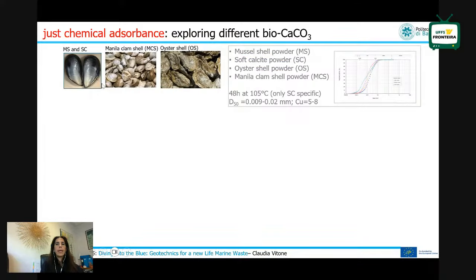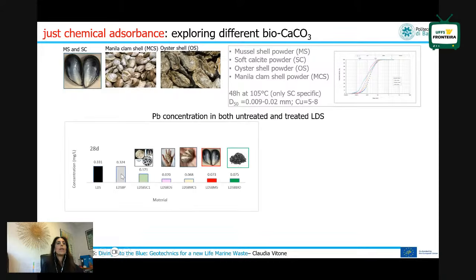So if we now also compare the behavior of mussel shells and soft calcite, but also the manila clam shells and the oyster shells and the powders obtained with this thermomechanical treatment, and we mix just the shell powder with the sediment, so without cement, this is just a chemical adsorbance for lead. This is the lead polluted sediment. So this is just the sediment. This is polluted sediment plus 8% of Portland.